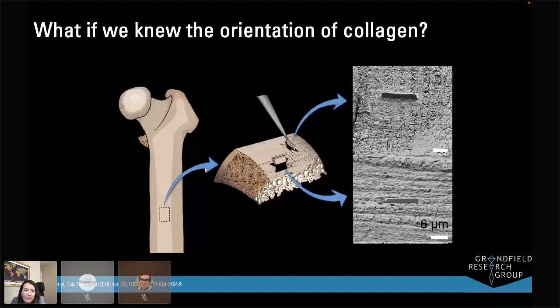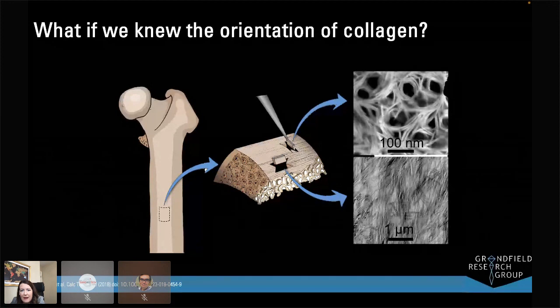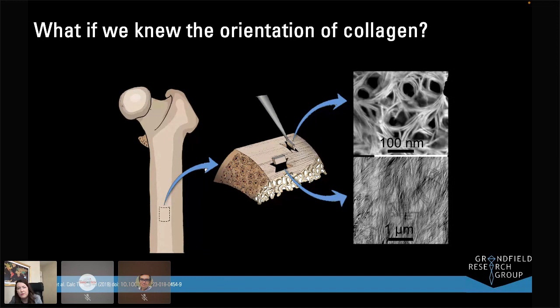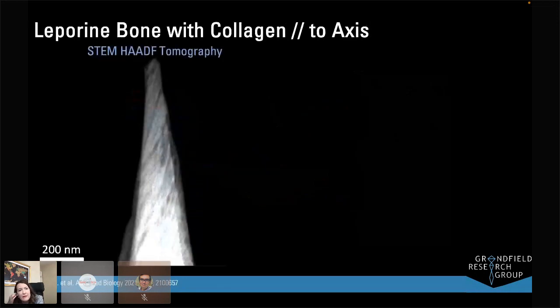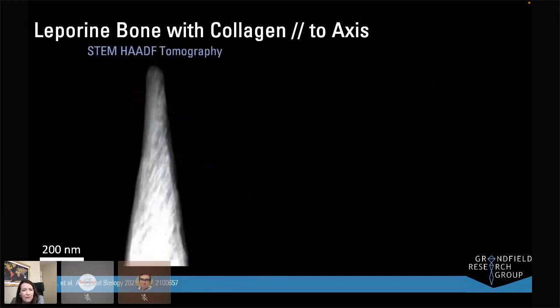This is possible if we take a long bone. By using a femur instead and slicing samples down perpendicular orientations, we know in advance the overall orientation of the collagen fibrils. So we did this to create an atom probe sample. We took a sample where we knew we could align the collagen fibrils along the length of the atom probe needle. This is an example of the image here.